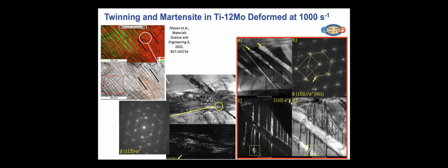Looking a little more closely at the Ti-12 moly with transmission electron microscopy and focused ion beam (FIB) foils, in this little region here, we actually see the twinning happening, and we see the martensite forming within these twins, which is pretty interesting. And then similarly, in the box here, we see a lot of very refined microstructure evolution that's kind of hierarchical at a really small length scale. So really this combination of TRIP and TWIP gives us this benefit of good elongation and improved properties for high rate response.